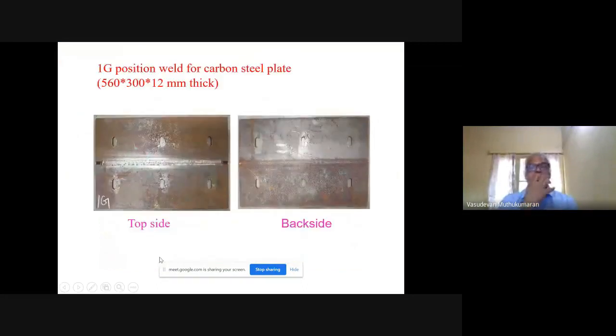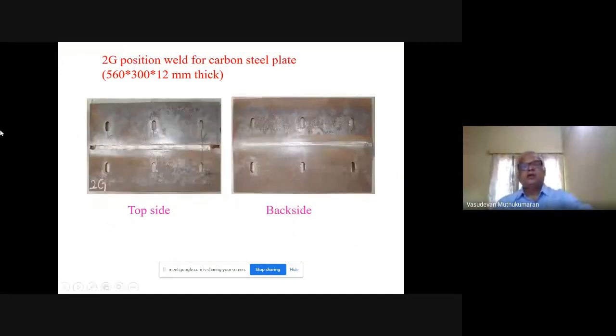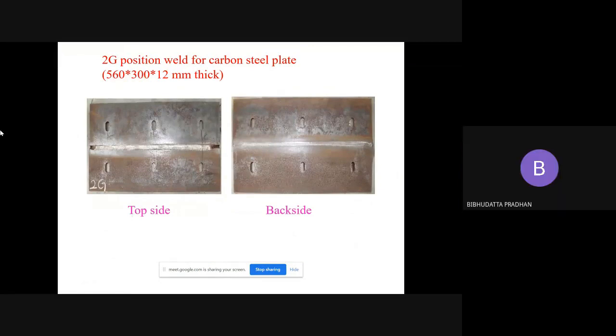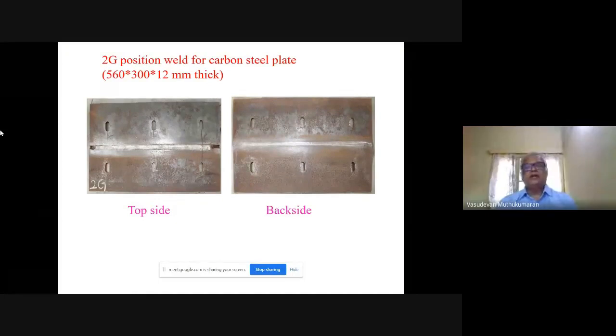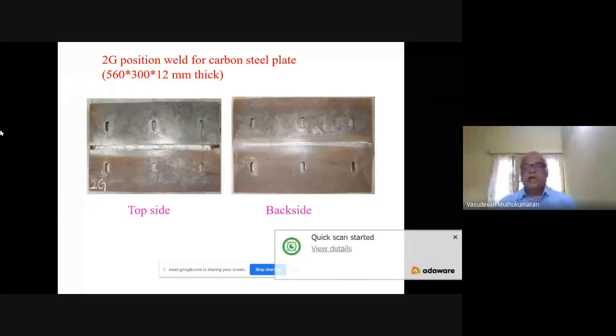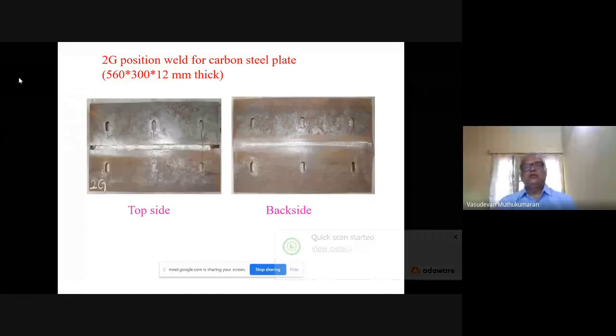Using the positioner, you can see carbon steel plates of this dimension, 560 by 300 by 12 mm thick. This is our top side. This is the back side. We passed radiography. We could successfully weld because it is an automated process with seam tracking and pre-programming of everything. We could do it very fast, and it is defect free also, and we could do it in the 2G position as well as 3G position and 4G position.